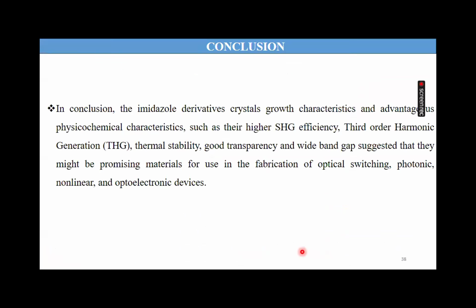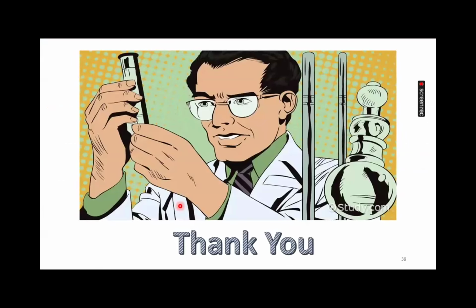Conclusions. In conclusion, the imidazole derivative crystal's growth characteristics and advantageous physicochemical characteristics, such as higher efficiency, third order harmonic generation, thermal stability, good transparency and wide bandgap, suggest that they might be promising materials for use in the fabrication of optical switching, photonic, nonlinear and optoelectronic devices.